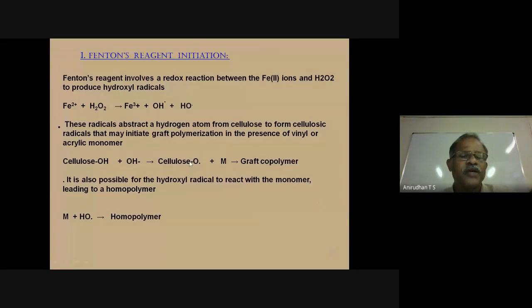So once again, I want to conclude like this. First we prepare this OH radical through this simple reaction, and this OH radical is highly reactive, abstracts one hydrogen atom from macromolecules, and we have a highly reactive macro radical. It will easily react with monomer to form a graft copolymer. So we have a backbone here, cellulose, and the graft is a monomer like acrylamide, acrylic acid, etc.